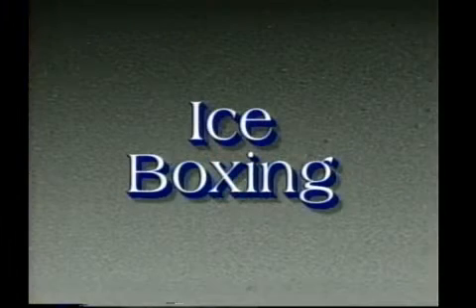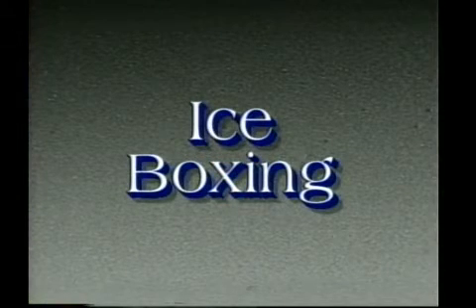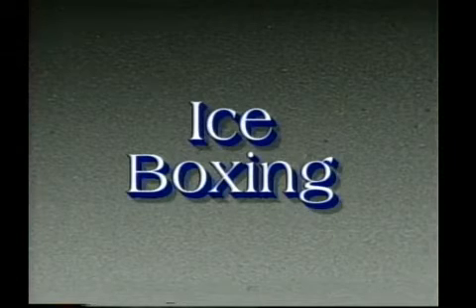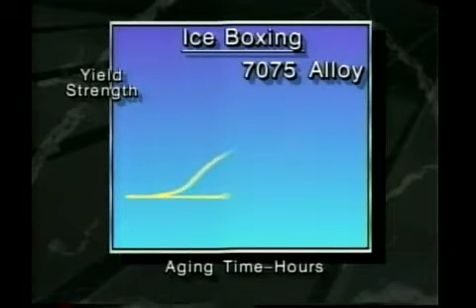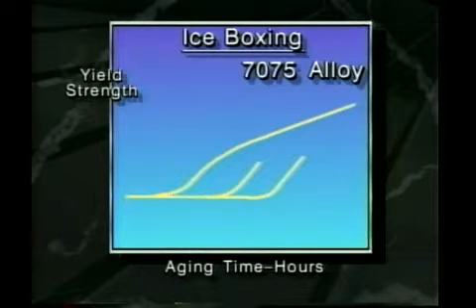The room temperature aging rate can be significantly retarded if a part is chilled immediately after quenching. The change of the yield strength versus aging times at room temperature, 32 degrees and 0 degrees, is shown for alloy 7075 in this next figure. It should be noted that these curves are plotted on a log time scale, and thus the temperature effect is more significant than it might first appear.